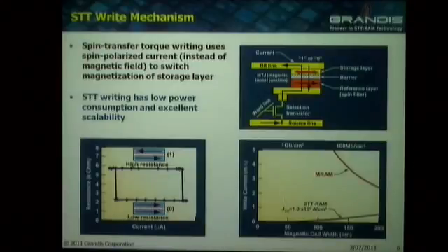And then I think the key difference compared with a conventional MRAM cell is the scalability. If you look at conventional MRAM, which was a very hot topic a few years ago, there are some MRAM cells in commercial production these days up to about 16 megabits. But the problem is when you scale MRAM below about 100 nanometers, the current you need in order to switch the cells, to create enough magnetic field, rises quite fast. Essentially, it's not scalable below about 100 nanometers or so. Whereas with STT-RAM, the write current you need in order to switch the cells reduces as you reduce the cell size. It's proportional essentially to the